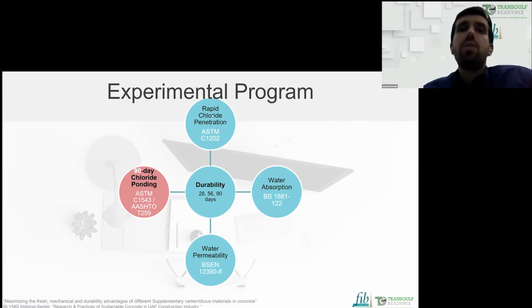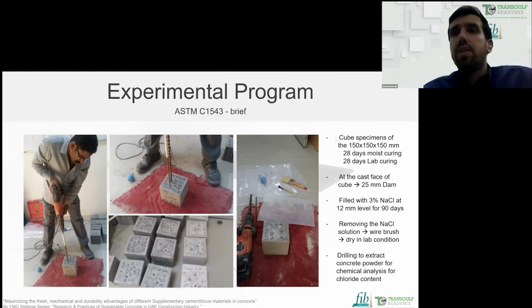For the water absorption test, rapid chloride penetration, water permeability, we added here a 90-day chloride ponding test, as per ASTM C1543. This is just a brief about ASTM C1543. It is not very common because of the time it takes for preparation, and the test is performed after 90 days, so totally it will exceed 90 days definitely, for the preparation and the age. So cubes were cast of 150 by 150 by 150, which are the common cubes.